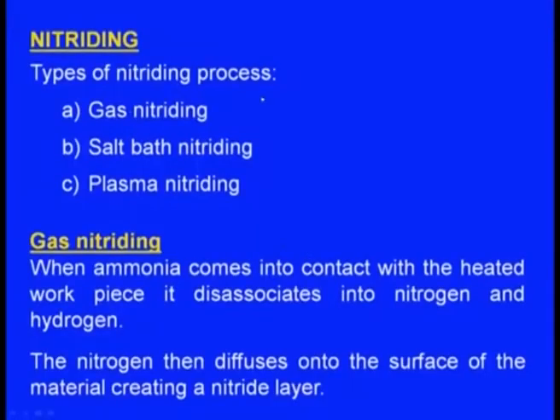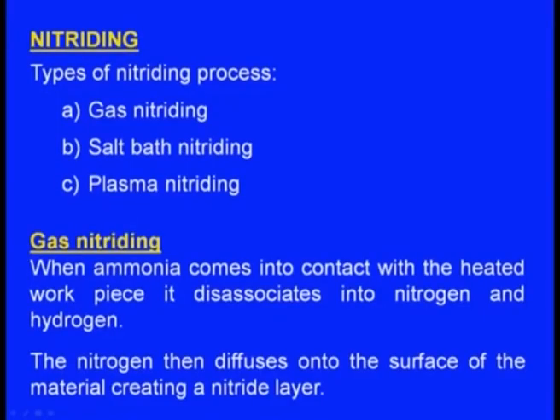Now, there are three types of nitriding process. One is gas nitriding, the second one is salt bath nitriding, the third one is plasma nitriding. In gas nitriding, when ammonia comes in contact with the heated workpiece, it dissociates into nitrogen and hydrogen. This nitrogen diffuses into the surface of the casting and forms a nitride layer. So, this is gas nitriding.